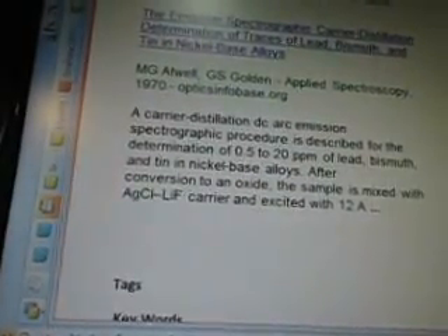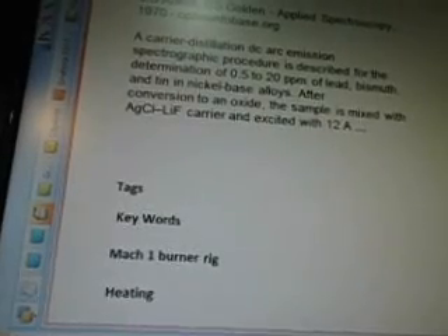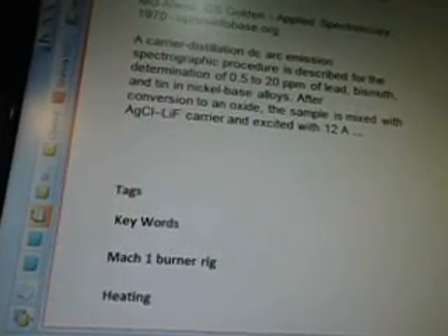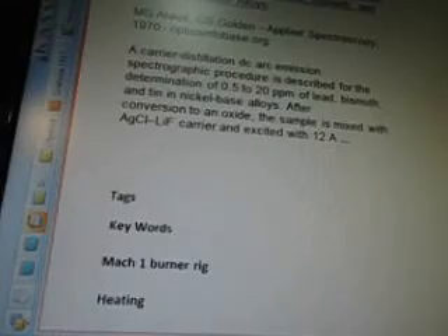The next is the emission spectrographic carrier distillation determination of traces of lead, bismuth, and tin in nickel-based alloys. From M.G. Atwell, G.S. Golden, Applied Spectroscopy, 1970, opticsinfobase.org. A carrier distillation DC arc emission spectrographic procedure is described for the determination of 0.5 to 20 ppm of lead, bismuth, and tin in nickel-based alloys. After conversion to an oxide, the sample is mixed with AgCl LiF carrier and excited with 12A.